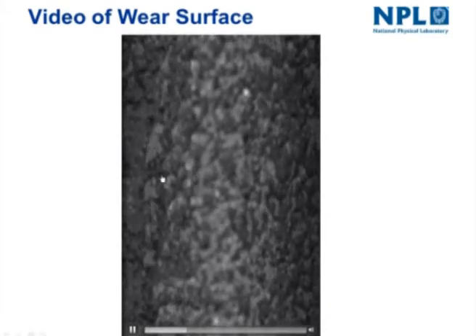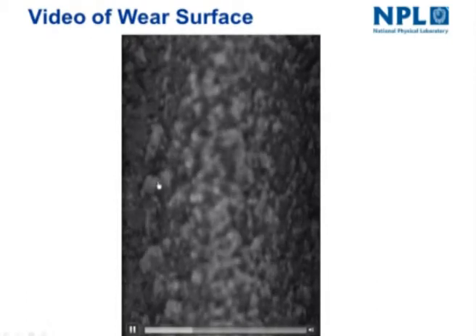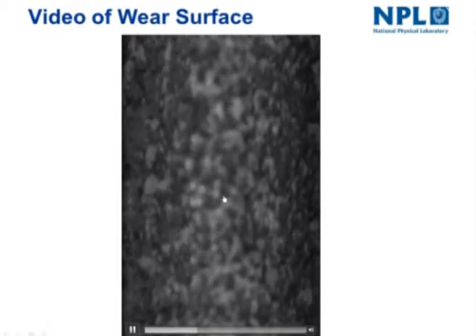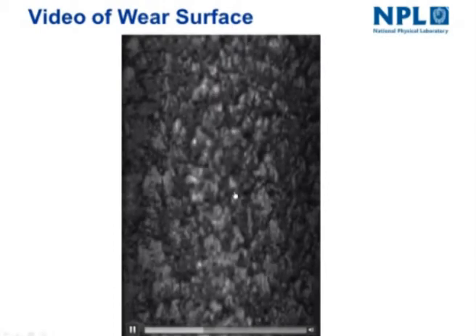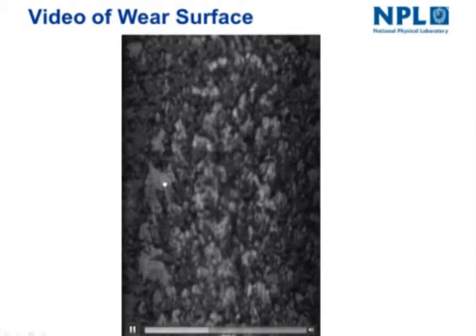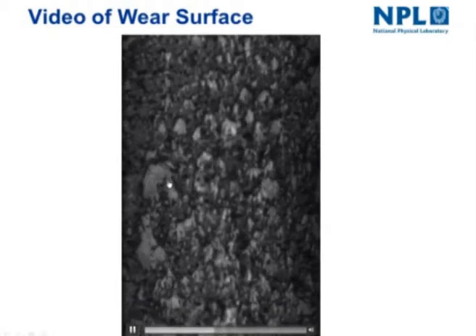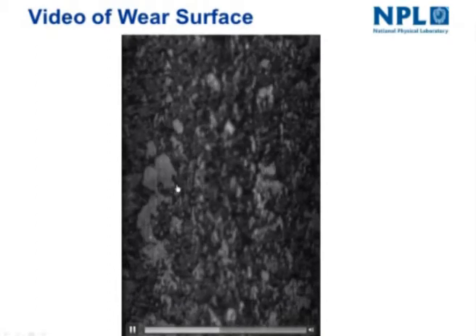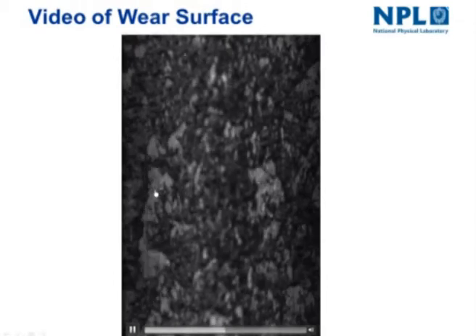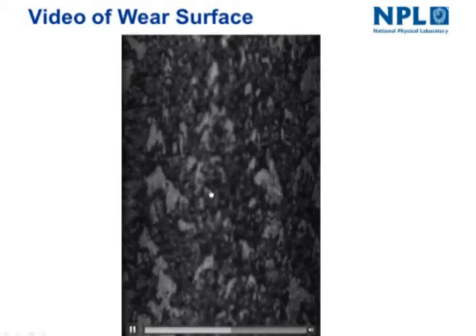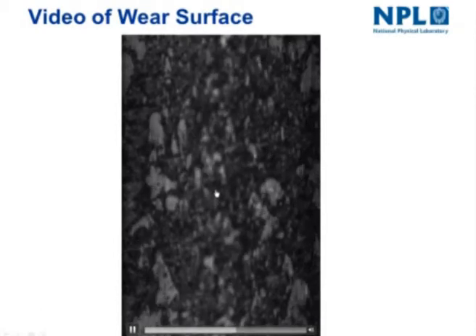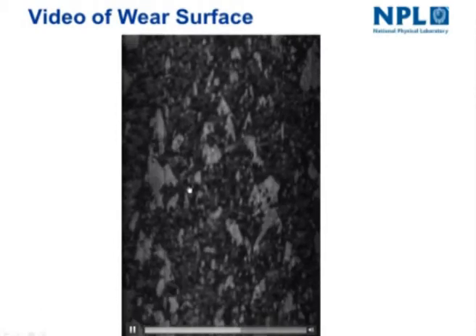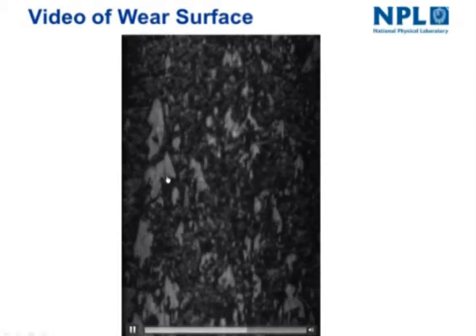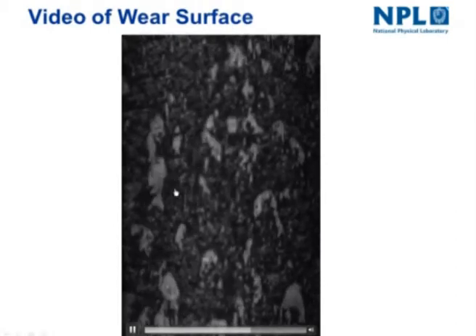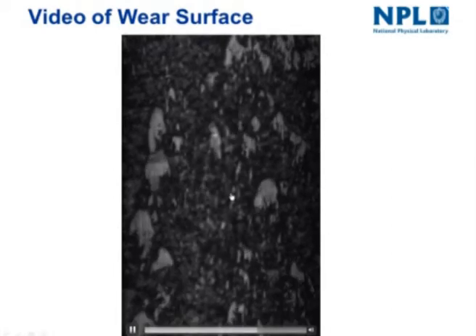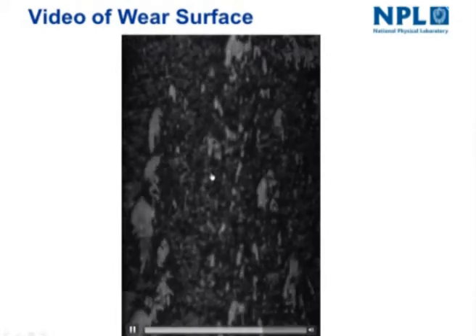And then later on we get these grey areas, out of focus at the moment. It'll come back into focus in a moment. Here we are. Build up on the surface, and then the remainder of this is the progression of these grey areas as we build up these transferred layers of iron oxide from the steel ball to the surface. And the importance of this is that for almost the first time, this enables us to see what is happening on the wear interface as it is happening, and that's tremendously important.